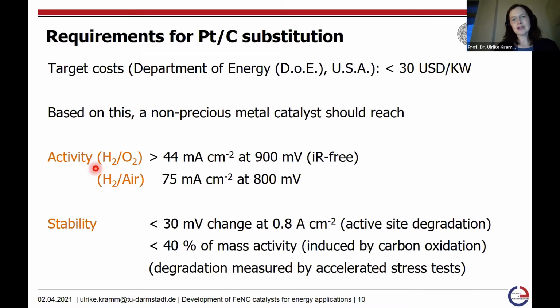Based on that, the non-precious catalyst materials should ideally reach above 44 milliamps per square centimeter at 900 millivolts, if this is iR corrected, in a hydrogen and oxygen fuel cell. For the real operation, which is in hydrogen and air, they should reach 75 milliamps per square centimeter at 800 millivolts. So this is the target with respect to the activity.